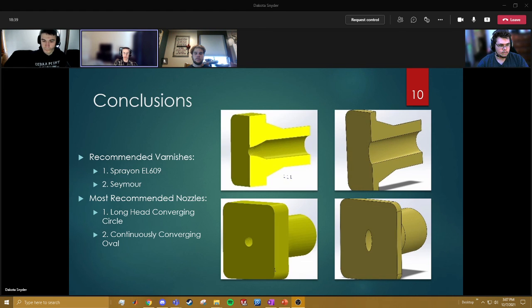The recommended varnishes are the Sprayon EL609 and the Seymour in a close second. Spray-on was selected in this experiment and is recommended in future testing. The best 2 out of the 4 recommended nozzles are shown here. They showed the most coating uniformity and had no application issues. These are the nozzles we recommend future students move forward with when considering initial designs.